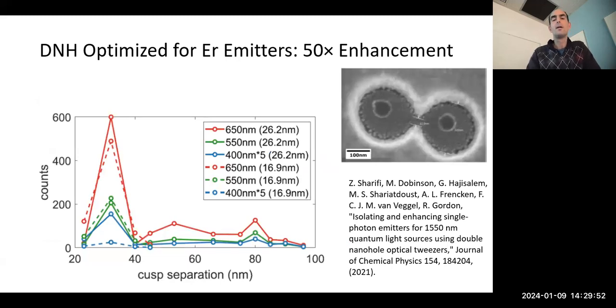I mentioned that previously we did rectangular apertures. The only difference in this work was to look at these double nanoholes that we've been using, which allow a lot more enhancement in the emission because we can make them much smaller than with the FIB, the focused ion beam machine. We basically found the separation in size that gives us the best emission.